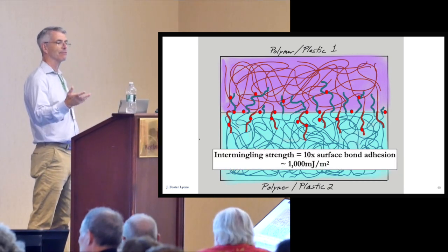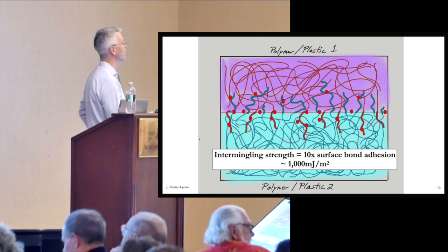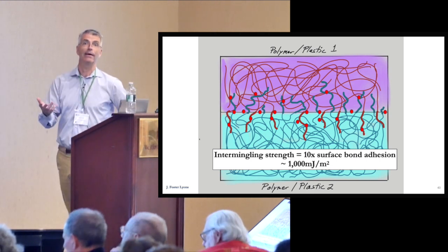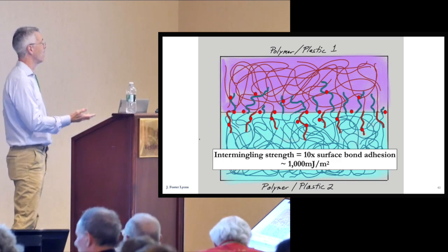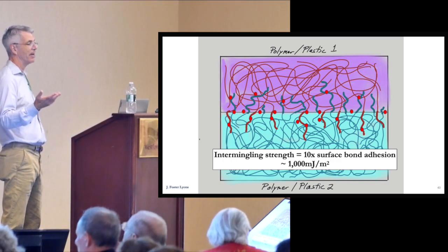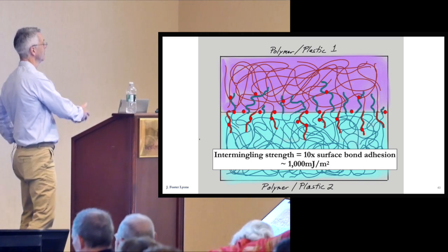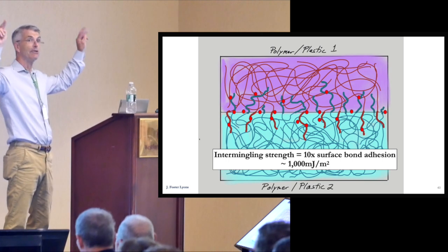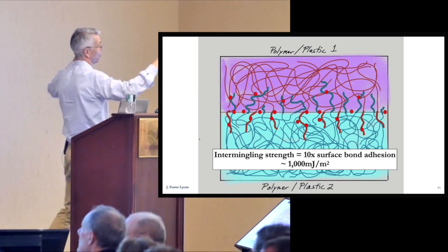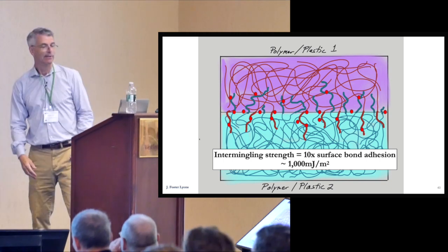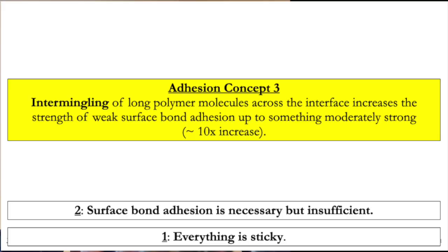So the strength of that sort of adhesion is about 10 times more than just surface bond or surface energy adhesion, okay? So now we're up in the range of about 1,000 millijoules per square meter, to give you some idea. We've jumped from about 100 to about 1,000 with just this intermingling, which happens with polymers, and we're always using polymers for the vast majority of our construction grade adhesion, all right? So that's adhesion concept 3. Intermingling of long molecules across the interface, the boundary between the two of them, increases the strength of weak surface bond adhesion up to something moderately strong, about a 10-fold increase, okay? So there we go.